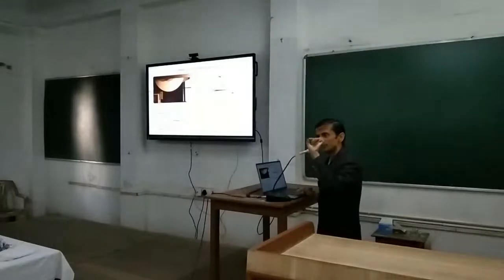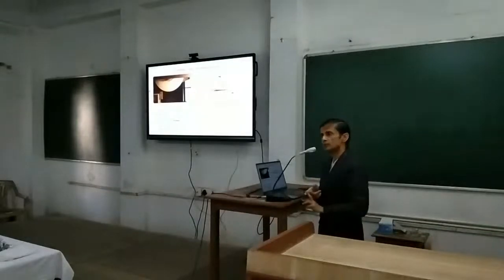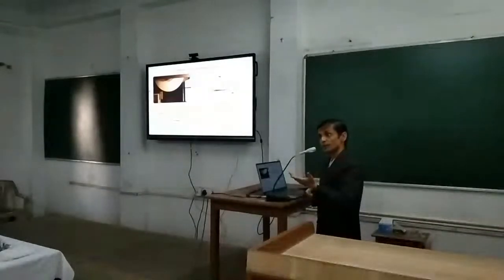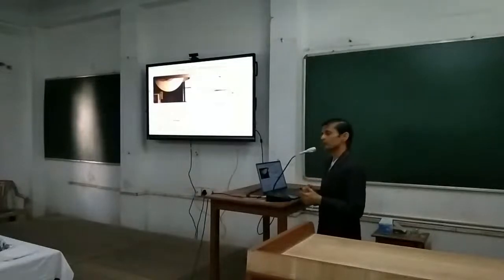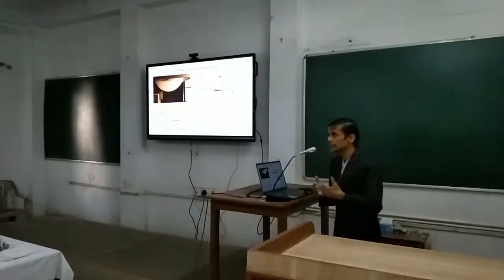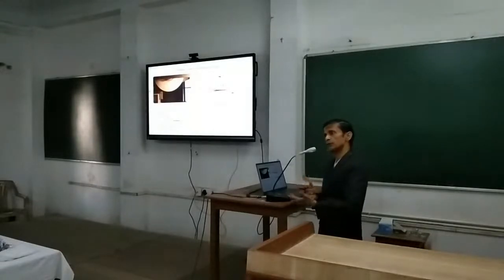The more it is towards the tip, the geometry is much better in terms of the sharpness of the grit. Right? So it is good that if the grit penetrates more, its specific energy, its energy consumption will be lesser, because if the grit penetrates more, it will remove the material much more in the shearing mode rather than the rubbing and ploughing. So what is happening? We increase the depth of cut, we increase the table feed, we increase the MRR, and we reduce the specific energy. But of course, if you increase the table feed, you increase the depth of cut, you may have to compromise the surface finish. So there is a play. You need to really optimize the thing depending on the requirement of the MRR and the finish.